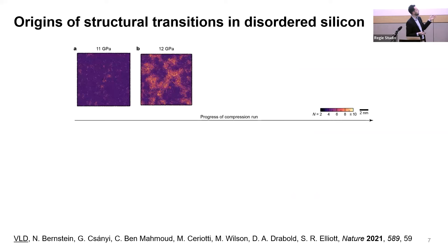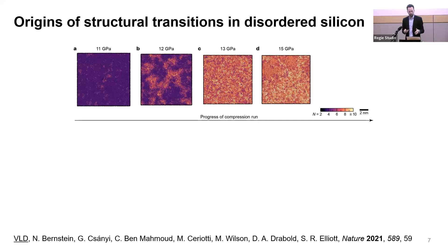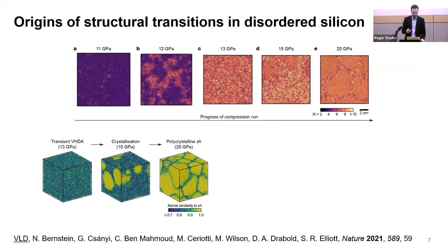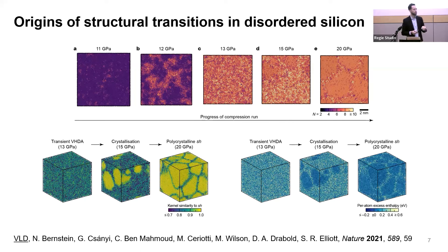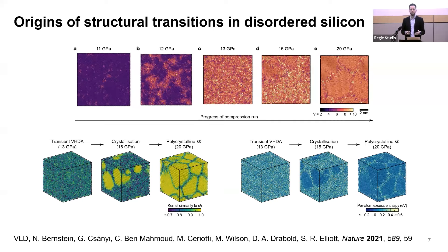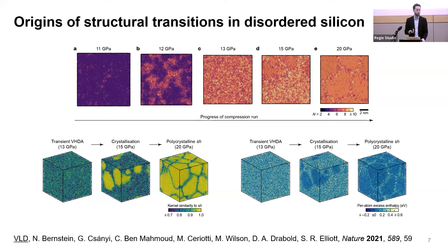You can take the simulation and analyze the sequence of structural transitions and the electronic properties. You can look at the similarity to crystalline phases — you see the simple hexagonal growing from the disordered phase. Using the local enthalpy, the crystalline regions are more favorable and appear darker, which makes sense because the crystal is thermodynamically favored. Silicon under high pressure is a specialized topic, but many other materials are polycrystalline, nanocrystalline, or have interfaces and grains — so this is an example of material simulations that just were not possible a few years ago.